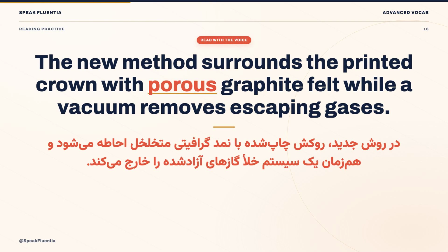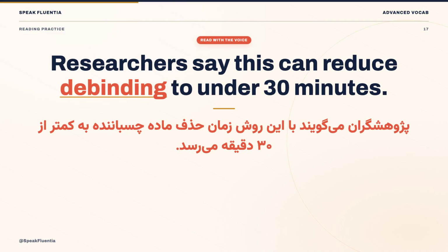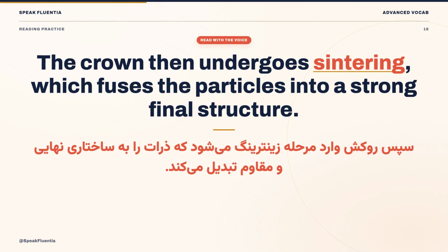The new method surrounds the printed crown with porous graphite felt, while a vacuum removes escaping gases. Researchers say this can reduce debinding to under 30 minutes. The crown then undergoes sintering, which fuses the particles into a strong final structure.